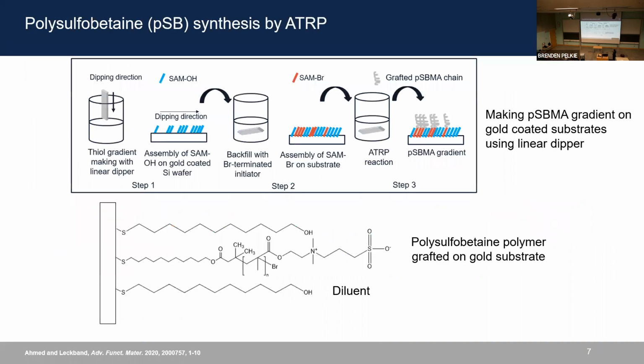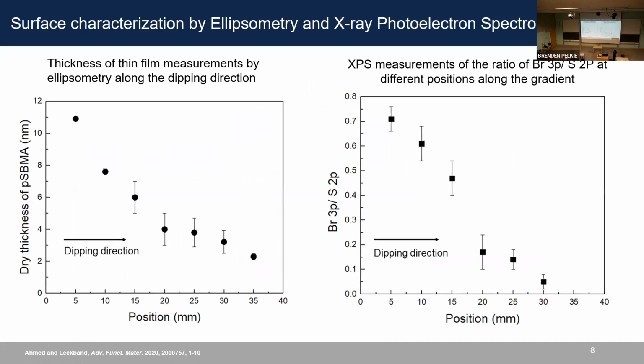So then we did the synthesis by using a linear dipper. We took the gold-coated silicon wafer to graft an OH-terminated thiol gradient along the dipping direction, and then backfilled with a bromine-terminated thiol, and then performed the ATRP reaction in a custom-made reaction vessel in an inert condition to grow the polysulfobetaine gradient on the substrate. And then we characterized the surface by using ellipsometry to measure the dry thickness of the grafted film. And we see a nice variation along the dipping direction.